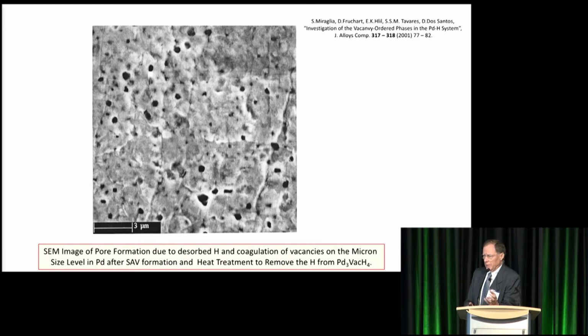then when this equilibrium structure, Pd3VacH4, is formed, and you subject it to vacuum and heat it and degas it, now you don't have the hydrogen in there to support the vacancy. So you're at a different location on the phase diagram. You're back to the metastable condition, and so those vacancies can conglomerate together, lower their energy slightly by doing so, and form pores. But this is a very high pore concentration, or a volume fraction of pores.